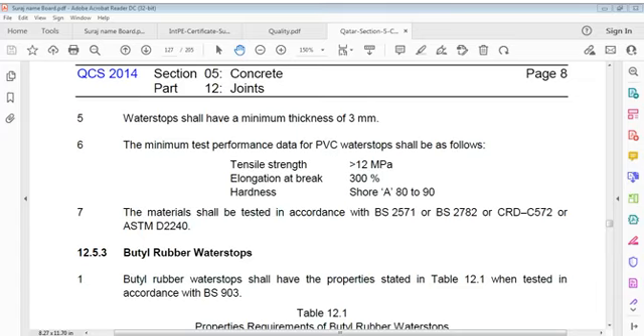Water stop shall have a minimum thickness of 3 mm, minimum test performance data of PVC water stop shall be as follows. Tensile strength more than 12 MPa. Elongation at break 300%. Hardness Shore A 80 to 90. Material shall be tested in accordance with BS2571 or BS2782 or CRD-C572 or ASTM D2240.